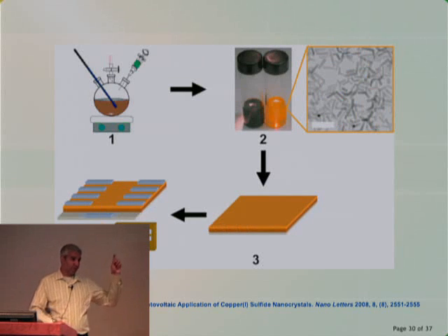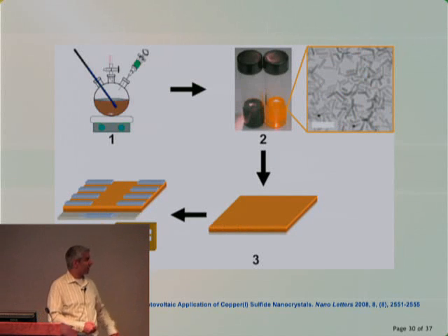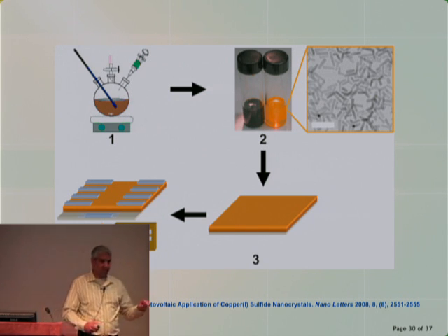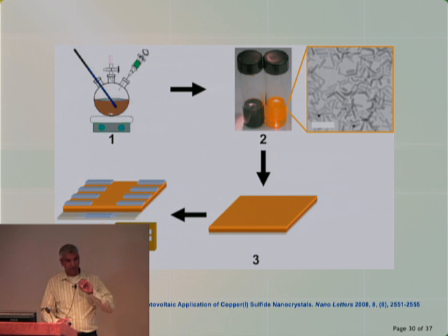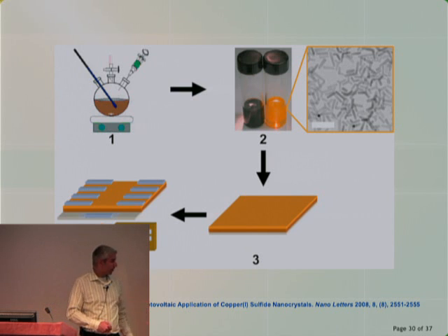So in order to go from that synthesis to an actual device, we take our material, and after some cleaning steps, first of all, this is a vial of my copper sulfide, and this is a vial of my cadmium sulfide with an associated transmission electron microscope picture. What we do then is we take these liquids and we sequentially deposit them on a conductive glass substrate. So that's what this is.